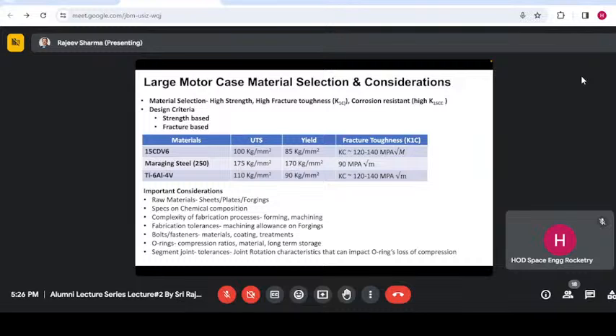And for maraging steel, 90 MPa root meter is a very good fracture toughness. Many of you may not have an appreciation for fracture toughness, but for a strength of this nature, 1750 MPa, 90 MPa root meter is mind-blowing. And this fracture toughness and strength does not come from carbon, mind you.